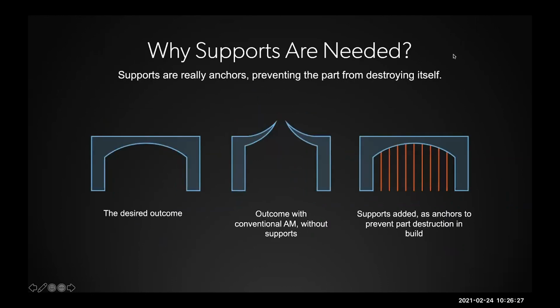So why do we need supports? A lot of these low overhanging features can't print on their own, especially in conventional metal additive manufacturing platforms. To exemplify this, here is a low overhanging arch type structure. If we try to print this without supports, the internal stresses and warp of the part will tear itself upward and could make recoating impossible unless we put these support materials on. And that's what we're showing in the red support structures that are essentially acting as anchors to keep the material constrained downward at a nominal height off of the powder bed so that we are able to continue recoating and build this structure.